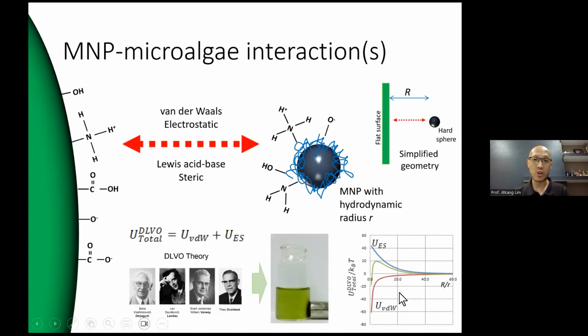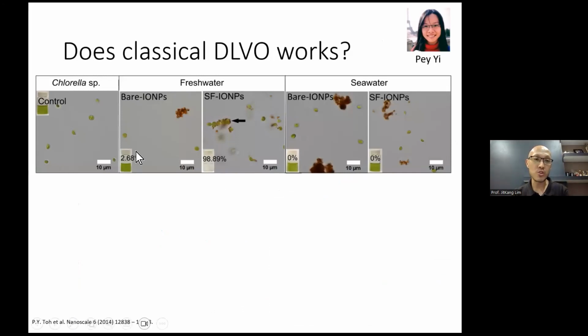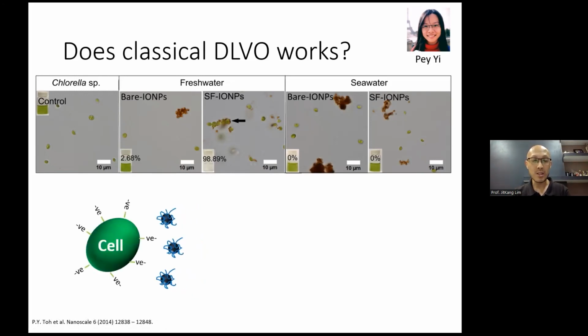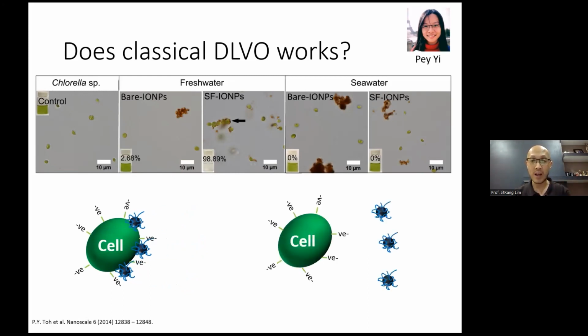We managed to construct the interaction potential between the particles and the cell. By doing that, we could not only experimentally confirm that the particles can attach onto the cell, but also theoretically predict whether our surface functionalization scheme can work or not. And so far, so good. For the freshwater samples, using Chlorella as one of the model systems, my student, Pei, managed to prove that by surface functionalizing the particles with PDDA, we could promote separation up to about 98 something percent. The theoretical predictions of DLVO theory, taking into account only van der Waals and electrostatic interactions, worked perfectly. The particle attachment was exactly as we predicted. Once we got it, we declared victory and published the papers, and we said the whole interaction scheme is driven mainly by electrostatic interactions.